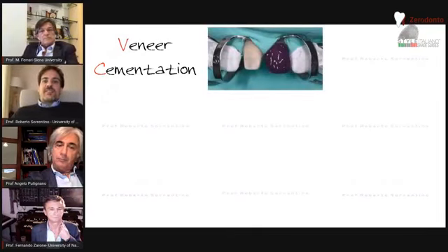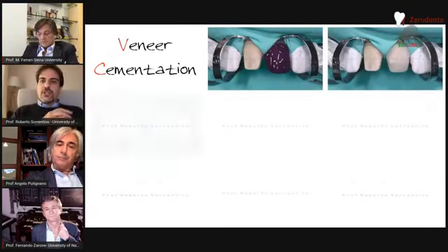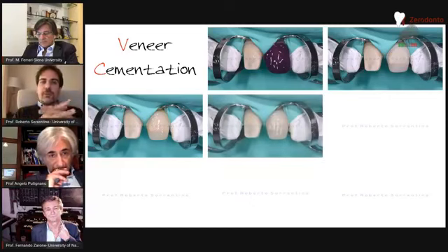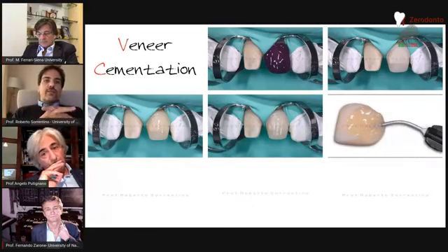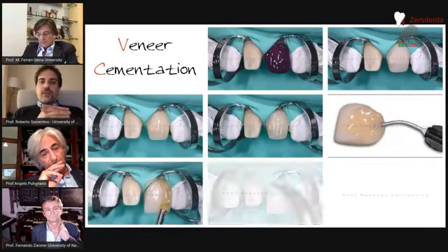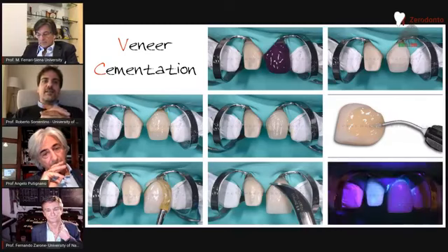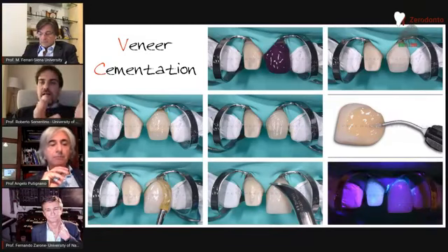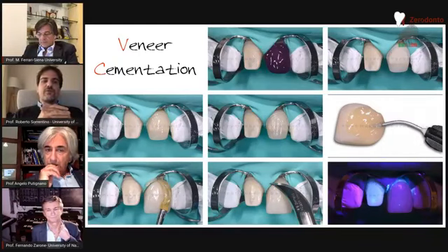Well, as regards the cementation of the veneer, since it has no primary retention by definition and all preparation periphery was kept in enamel, I chose a conventional 3-step total-etch approach with a universal adhesive system and an aesthetic resin cement, namely a dual-curing resin cement, so as to avoid marginal discoloration over time.